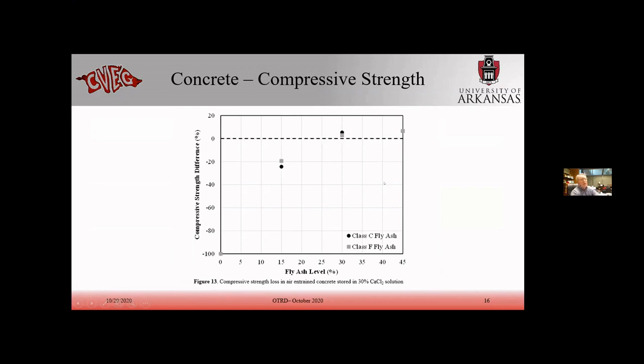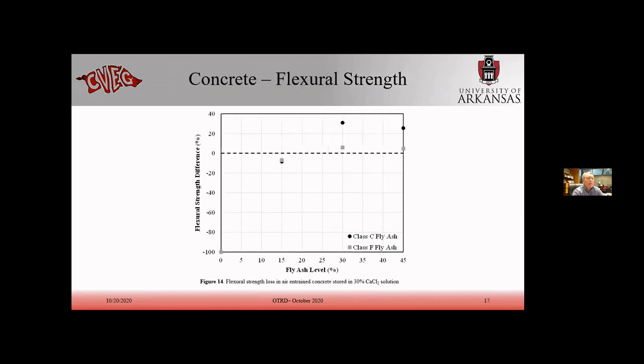So just quickly here, we'll go over this. This is compressive strength difference. And we labeled this as 0 just because those Portland cement only mixtures really couldn't be tested after the 202 days. But at the fly ash level of 15%, we saw a decrease of 20%, and then they were close to about the same at 30 and 45% fly ash.